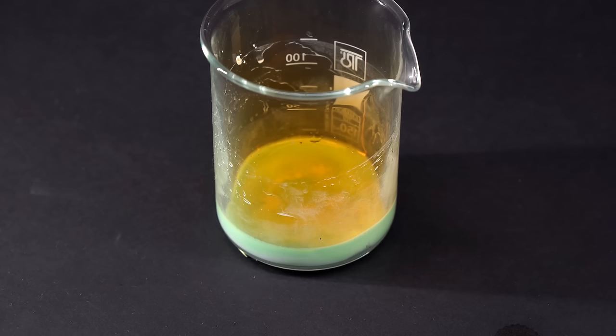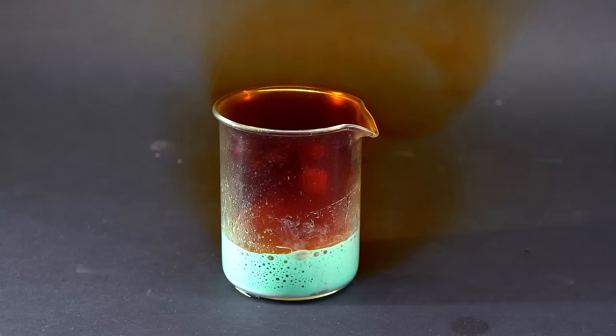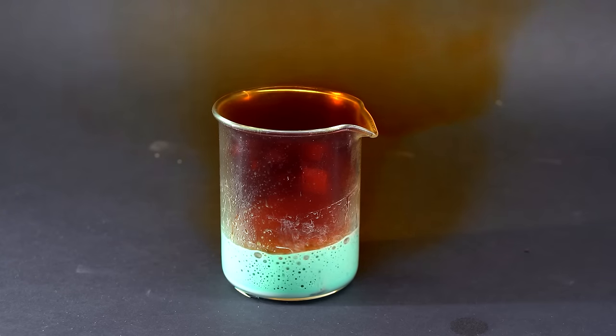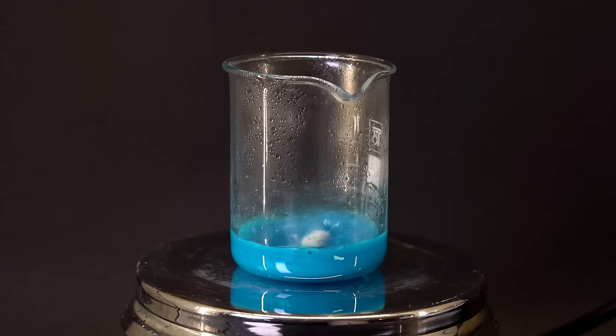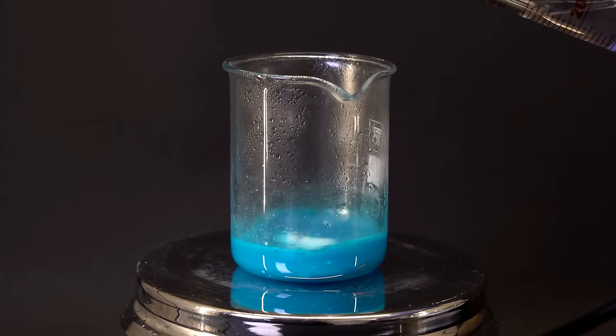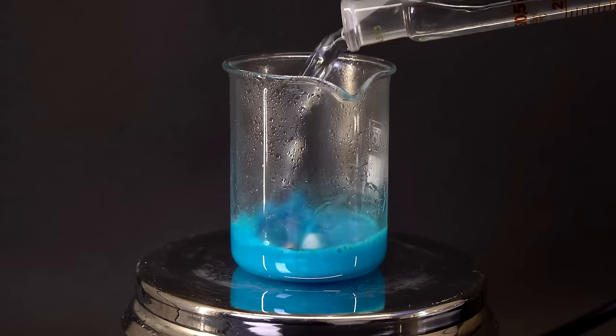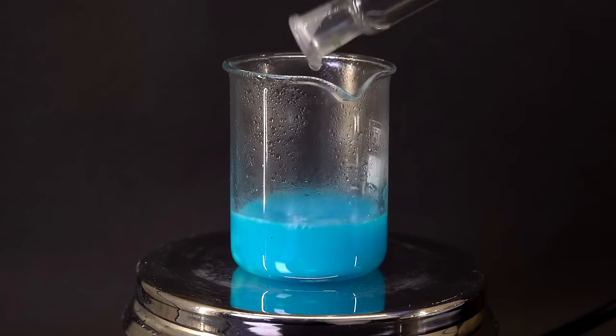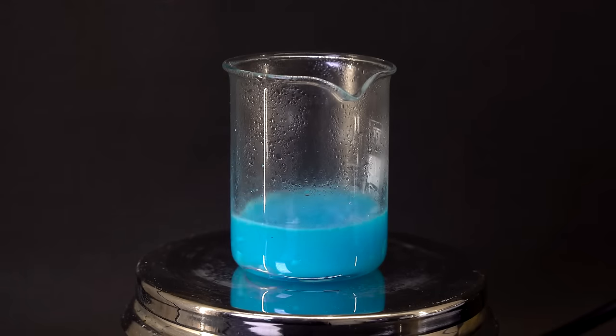The copper immediately dissolves in the nitric acid, forming copper nitrate and heating the mixture, thus helping the yttrium oxide dissolve better in the acidic environment of the solution, forming yttrium nitrate. After dissolving the copper and most of the yttrium oxide, I start to heat the mixture on a magnetic stirrer and add barium nitrate into the solution. After which, I add a little water to help all the components dissolve better.